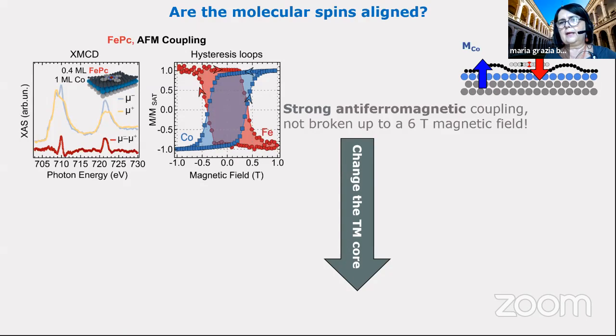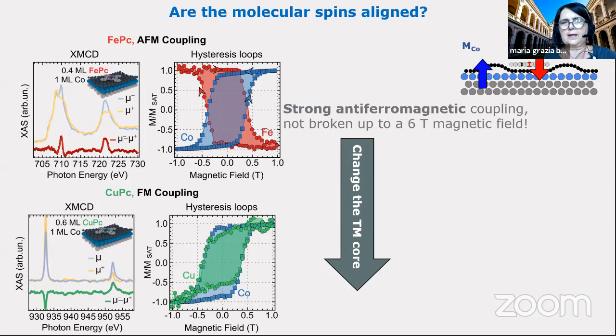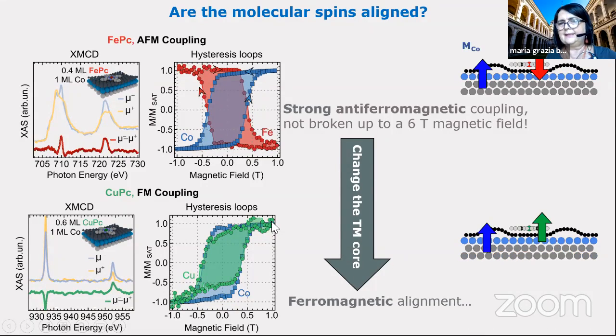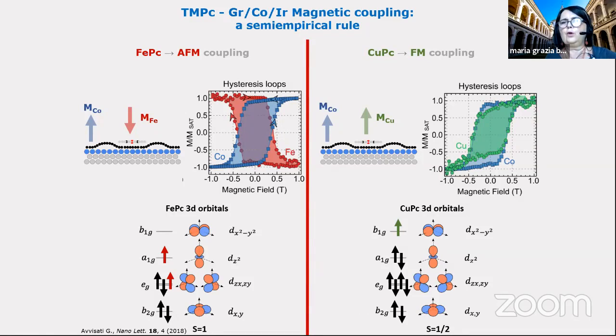Then we change the transition metal core. So we put copper instead of iron. In this case, the dichroism has a different sign, see here. And in this case, you will have a ferromagnetic coupling. So if you calculate the hysteresis, you have the same direction of the easy magnetization axis of copper and cobalt, and the alignment is the same, so it's ferromagnetic. So this is interesting, but then there is the semi-empirical rule. If you look at the orbitals that are carrying the spin, for iron phthalocyanine they are perpendicular to the molecular plane. In the other case, they are parallel to the molecular plane. So the first case is antiferromagnetic, the second case is ferromagnetic.